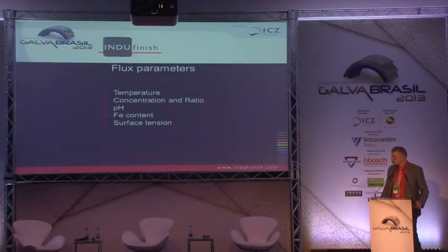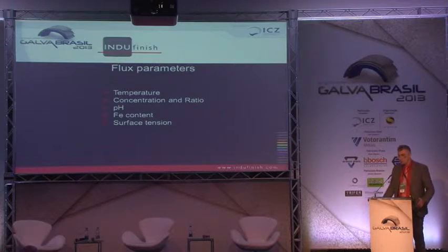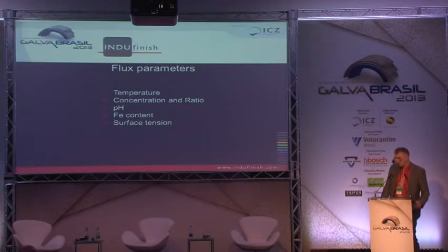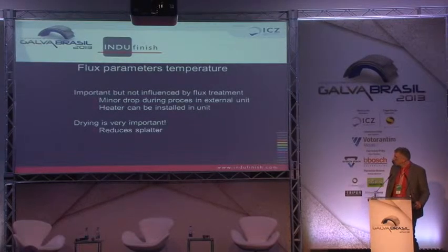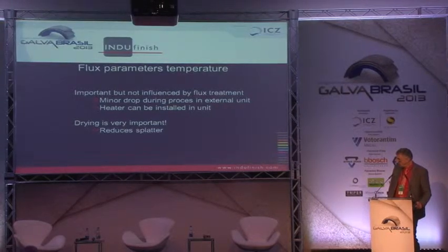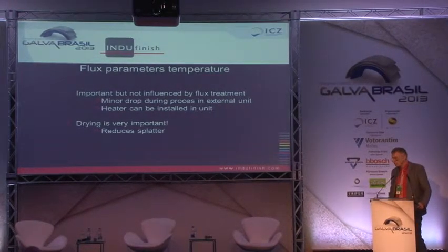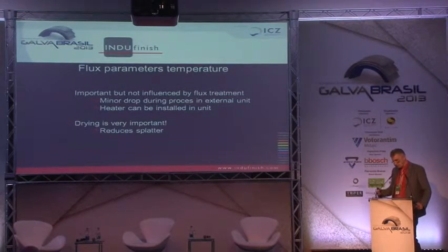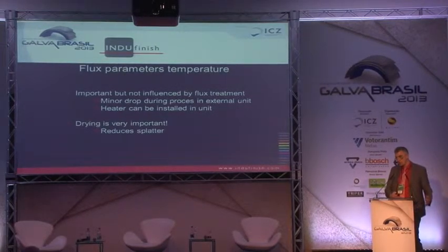We started again to investigate all the parameters that we thought were important for your flux treatment, as in temperature, concentration ratio, pH, iron content, and surface tension. Temperature. Our flux cleaner won't affect the temperature of the flux. If we're taking it out, circulating it and pumping it back over a very large distance, maybe you will cool off some flux, but until now we didn't experience that.